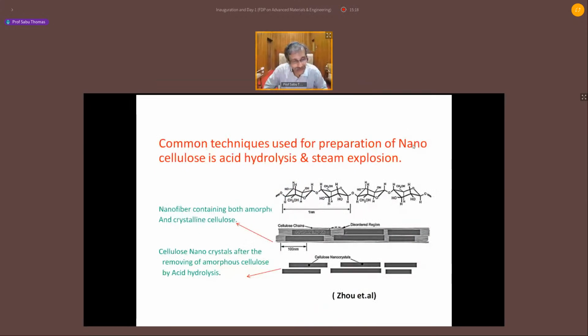Let me quote some of the work. Professor Zhou and co-workers subjected plant fiber to acid hydrolysis and a steam explosion process. You know what they made? They made two types of material. One is long nanocellulose. When the acid they used is mild acid, you see, this is a long nanocellulose. You have crystalline, amorphous, crystalline, amorphous. But when Professor Zhou used strong acid, the strong acid could eat away all the amorphous region. This is amorphous region, and he got short nanocrystals. So you can get either long nanofibers or short nanocrystals.